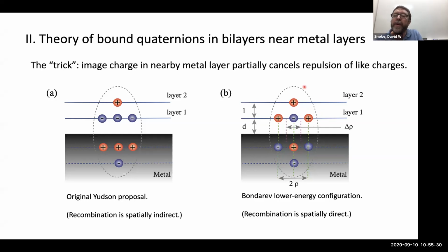And of course, the other thing that's going on is because of the bilayer, some of this charge is pushed away so that the repulsion of this electron to that electron is pretty weak because it's far away. Okay, so this is what we want to try to look for. So Bondarev did the calculation, and there are 2 parameters here. Keep in mind, there's the distance L, which is the distance between the 2 layers. So this is a 2D material, this is a 2D material. And then there's the distance D to the metal.